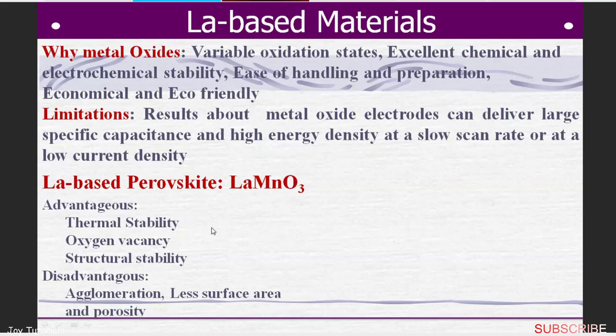This material has some advantages — thermal stability is high and structural stability is also very high. But there are some problems like agglomeration, since it needs high temperature to prepare, which can cause agglomeration. If agglomeration is more, sometimes it may not be useful or may have less surface area. When you want to make a nanomaterial form, only then can you have a higher surface area or make it porous. These are the problems in this material.